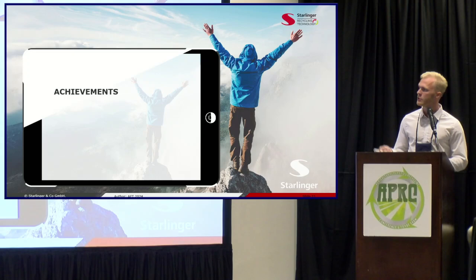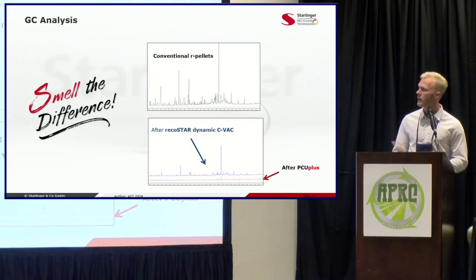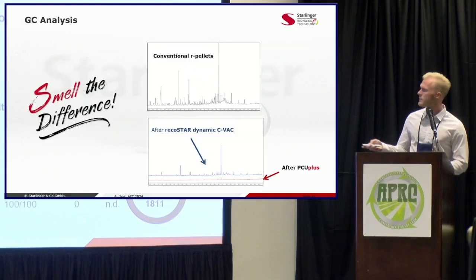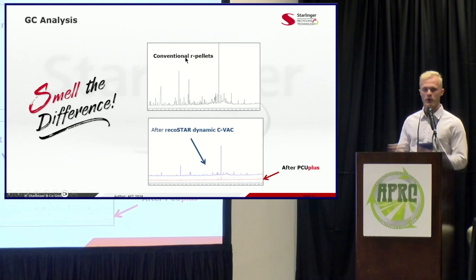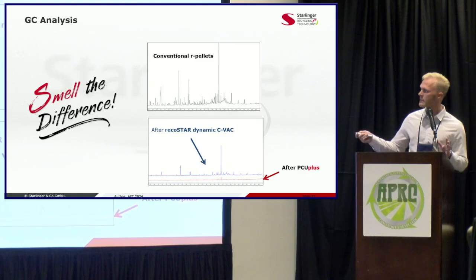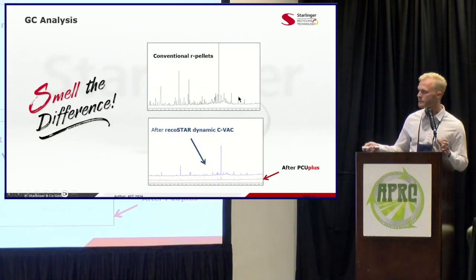So what are some of the achievements that I can show? So this is a GC analysis comparing conventional pellets that were extruded on a Starlinger extruder, but with our typical degassing, so our single screw vented 40 L over D extruder without the CVAC. And you can see that the GC analysis shows quite a bit of low molecular weight compounds and some medium ones with a large spike here in the middle.